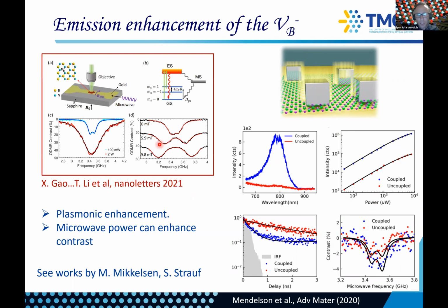And here, in parallel, the group of Tongcang Li from Purdue, they actually went the other way around to enhance contrast. And so they actually made the VB and put it directly on the microwave antenna, and they immediately saw a contrast of about 40%. And so you lose some of your hyperfine information here because there is a lot of microwave power. But for some applications where you don't care about your hyperfine, you actually have a very good ODMR signal.